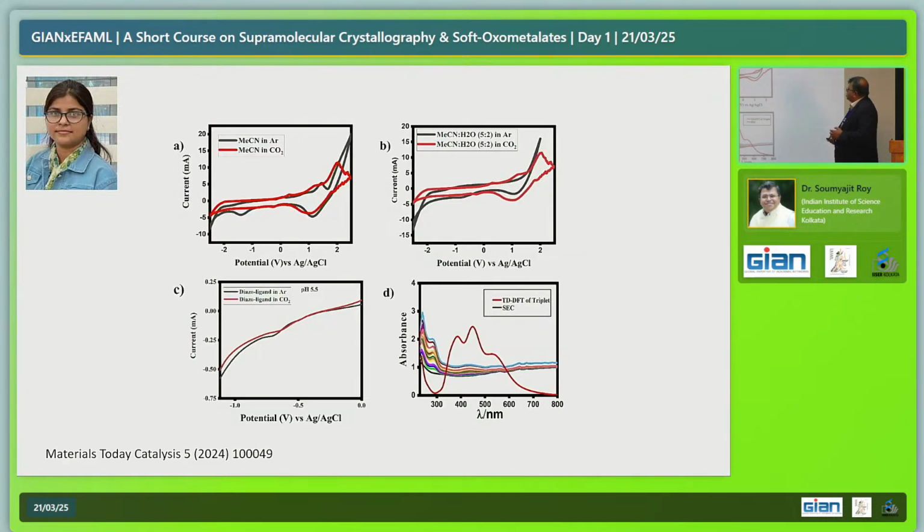For example, when you do electrocatalysis, how do you know that you have any reactivity going on? This is a very simple question, right? So the first thing that you can do is run a linear sweep voltammetry curve, just a simple LSV curve, right? And then you run it in argon, where you have no reactant, and then you run it in carbon dioxide, which is your reagent. If your reagent is nitrogen, you run it with nitrogen.